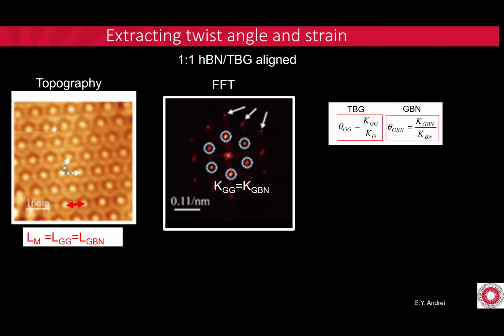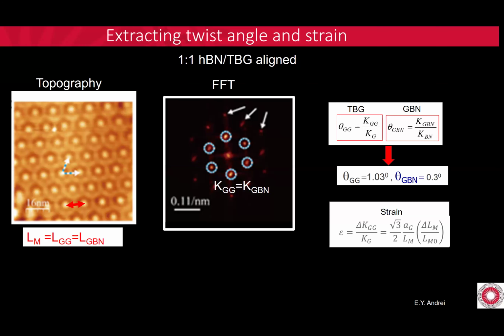Okay, here's an example. Here we don't see any dark spot. This is a 1-to-1 alignment, so L Moire, L_GG, is equal to L_GBN. In reciprocal space, you see the K vectors of the two are on top of each other. And we can calculate the twist angles, they're 1.03 in this case and 0.3. But there's strain and we can calculate the strain. In this particular example, we have about 0.3% strain. Every sample we can analyze and get out the numbers.